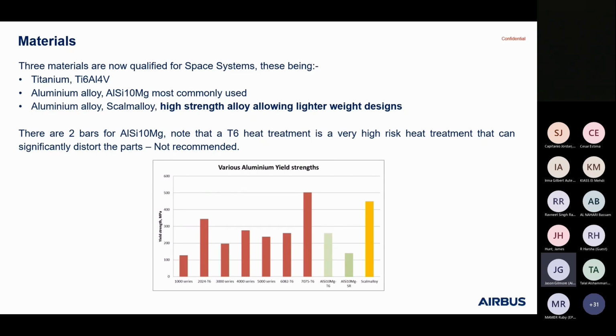That took place in 2019, and this Scalmalloy, as you're probably familiar with, is a high strength alloy allowing lightweight design. So the chart on the bottom shows the red bars represent, in order left to right, the 1000, 2, 3, 4, 5, 6 and 7000 series aluminiums. The axis on the left is yield strength, so we can see a good old 7075 is around about 500 megapascal yield strength. Problem with that material is the corrosion properties are not great. I think it's due to the high copper content.